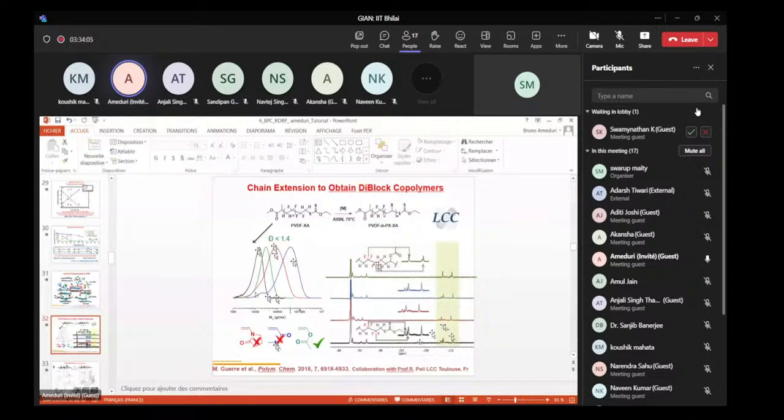However, with vinyl acetate, which is very well controlled by xanthate, you can see first that the GPC has a very narrow trace. It's less than 1.4 for a diblock copolymer, which is rather exceptional in this case. And when you look at the fluorine NMR, the little signals on the left disappeared, showing a good presence of the second block assigned to the VDF. So the CH2-sulfur or CF2-sulfur end disappeared through the presence of vinyl acetate.